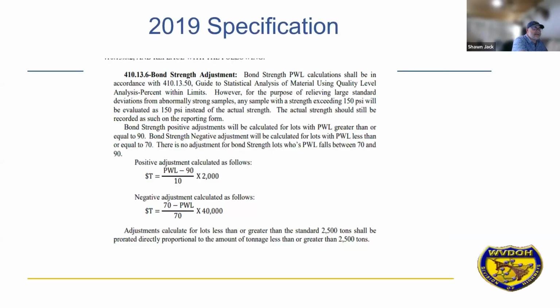So in 2019, along came our current specification, and this time around we stand silent on tack coat application. But now the negative adjustment is in effect for every sample. And we also offered an incentive for good bond strength results. So you can see our positive and negative adjustments listed there. And those are still the same adjustments that we use today.